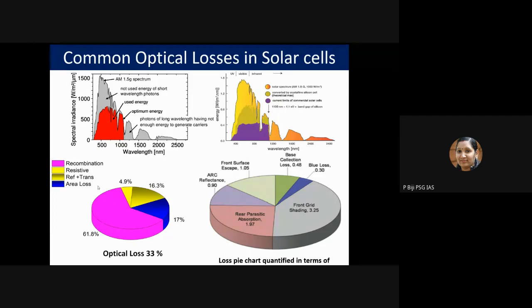Now this pie chart on the left side shows the shares of various losses. This pink one, the main loss, is coming from the recombination and the resistive loss, which comes under the electrical loss. So that we will not consider at present. But the optical loss contributes almost 33%, which means that we can still further reduce this optical loss by adopting suitable metallization strategies.